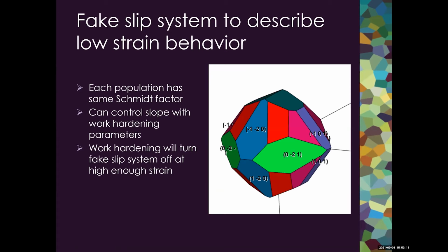And so we created this fake slip system to mimic this unknown deformation mechanism, where the figure to the right here is just the slip system with the 30 planes and directions, which allows us to have every grain population have the same Schmidt factor. We can then use the work hardening parameters to model the slope at the beginning of the EPSC simulation. And as we continue deforming, the strain increases, and at some point, the slip system will turn off.